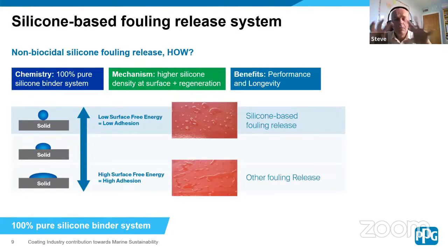Now, you may not be totally familiar with this type of technology, but in the schematic on the left-hand side, we see a droplet of water being placed on a surface, a substrate that likes water. So the water droplet spreads out, it wets the surface. The next droplet, it doesn't quite like this surface as much as the first. So the contact angle is changing. It's trying to minimize the area of contact of exposure to the substrate. And at the top, we see a droplet of water that does not like the surface at all. So it tries to ensure it has as minimal contact as possible.